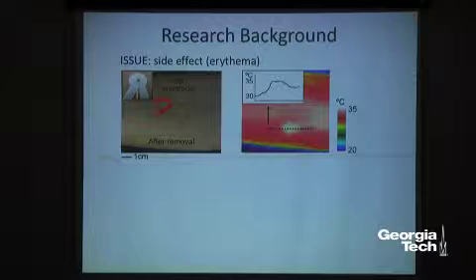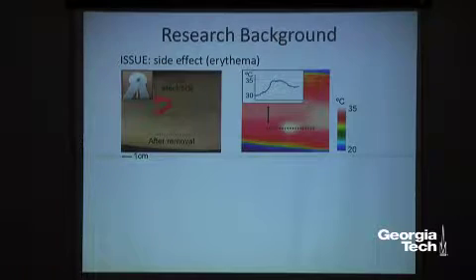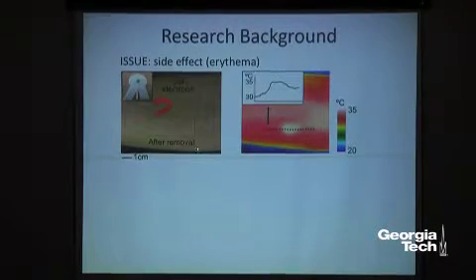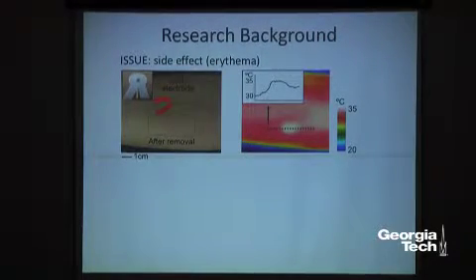So sadly, if you wear this device for long term, like more than 5 hours, more than a day, you can see this problem. It's my skin, and I put this electrode on my skin, again with the gel and metal, and I use this tape to put on my skin. After 5 hours, I detach it, and I use this infrared camera to see the temperature variation over my skin. What do you see? So that's the location where I put this electrode with the gel. Now you see this elevated temperature. Right? They can cause skin irritation, skin redness, and allergic reactions. Right? So that's bad. Nobody wants to wear this by irritating your skin for a long time.